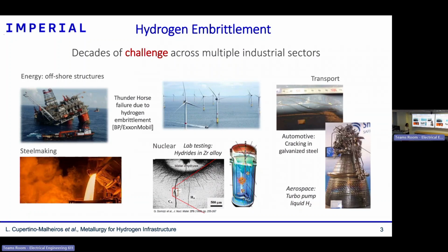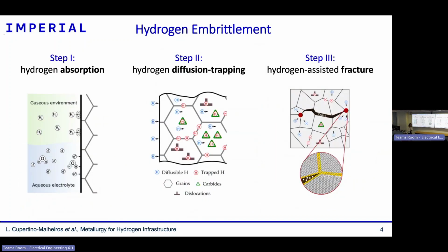Okay, but what is this challenge? Specifically, when we are talking about hydrogen embrittlement, there are 3 steps involved. So the first one is hydrogen absorption. Sometimes it's neglected by the mechanical and material engineering community, but if the alloy making people have done a good job and it didn't start with hydrogen in your alloys, for hydrogen embrittlement to actually take place, hydrogen needs first to enter alloys, because hydrogen embrittlement is a problem when hydrogen is in the bulk of alloys.